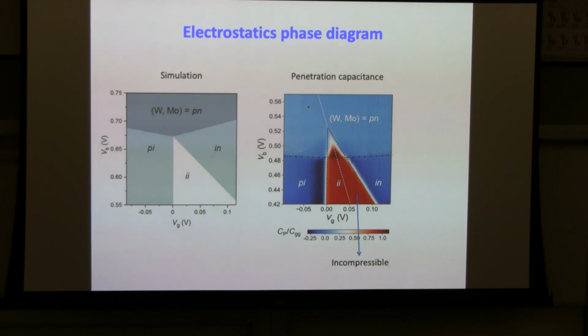And now we can compare this map with the electrostatic simulation, and mostly it agrees pretty well. You get this II region here, which is charge incompressible because you have no charge in either of the layers, and you have the IN region and PI region, electron doped and hole doped, so it's compressible. And you also have the PN region here, which is also compressible. But if you look a little more closely, you can see that the injection threshold for the electron and hole pairs is pulled down by about 30 millivolt compared to the tip where the gap is closed. Compared to here, the electron hole injection threshold should be exactly aligned to the tip, but the experiment shows that it's pulled down from the tip by about 30 millivolt.